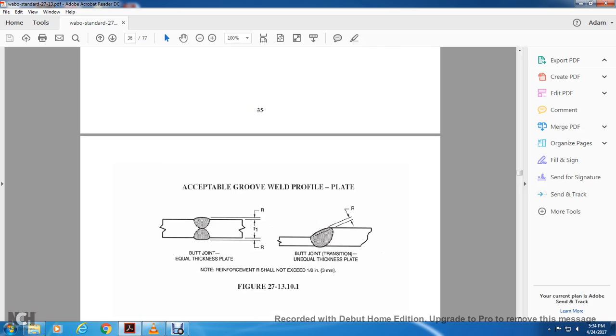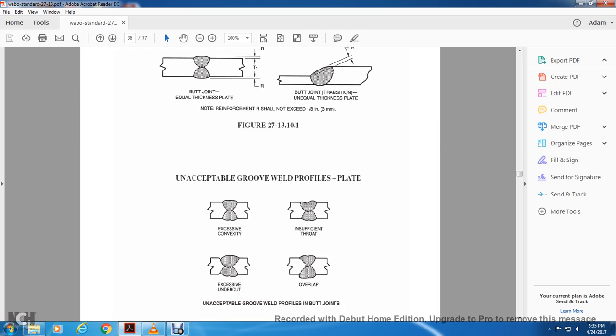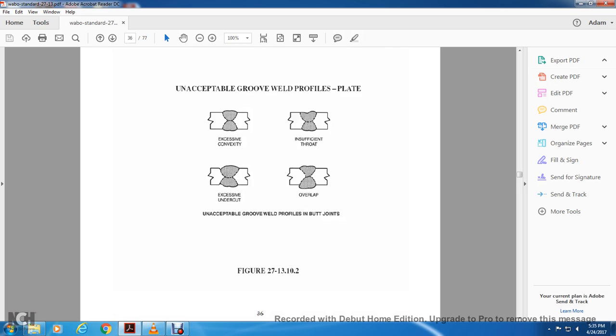Acceptable groove weld profile plate. Butt joint, equal thickness plate. The T1 R butt joint transition, unequal thickness plate radius. The reinforcement R shall not exceed 1/8 of an inch maximum. Unacceptable groove weld profile plates: excessive convexity, insufficient throat, excessive undercut, overlap.